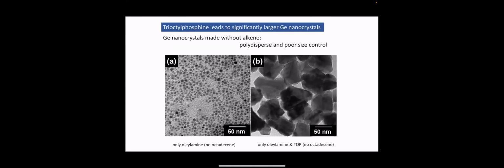So if we make germanium nanocrystals with a mixture, say, of oleylamine and trioctylphosphine, if there's trioctylphosphine in there, you end up making much, much larger germanium nanocrystals, these giant, almost bulk kind of germanium particles. And the trioctylphosphine is interesting because it doesn't seem to just speed up the reaction. The TOP seems to bind and complex with the germanium, actually slowing down the nucleation event, but then once it happens at higher temperature, at say 180 or 200 degrees C, then you get this burst of growth and nucleation.